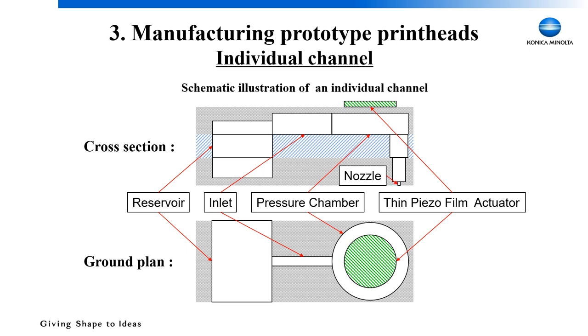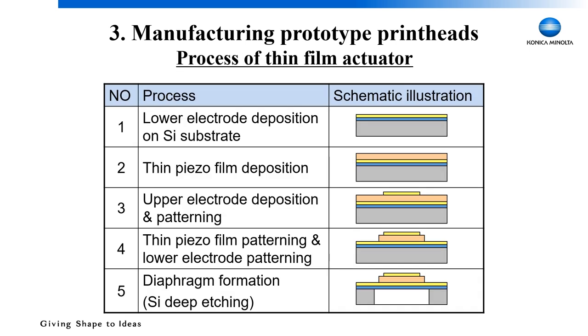This table shows the manufacturing process of the thin film actuator. At first, a lower electrode was deposited on a silicon substrate. Secondly, a thin piezo film was deposited on that. Thirdly, an upper electrode was deposited and patterned. Next, the thin piezo film was also patterned and the lower electrode was patterned. Finally, a part of the silicon substrate was removed by the silicon deep etching method and a diaphragm was formed.